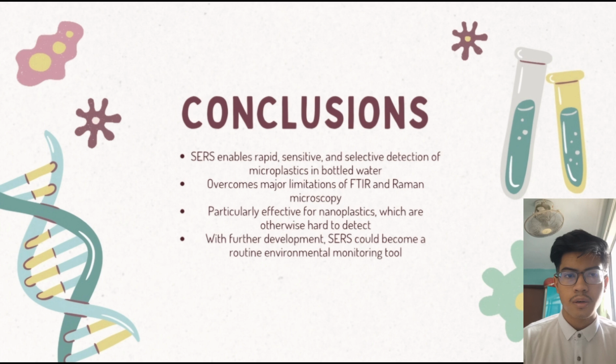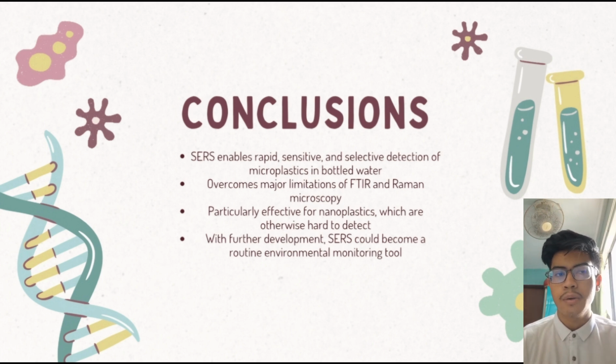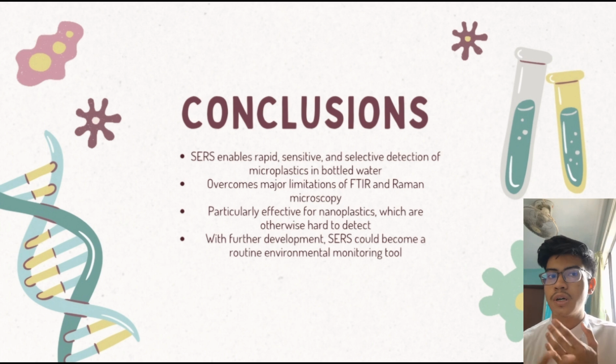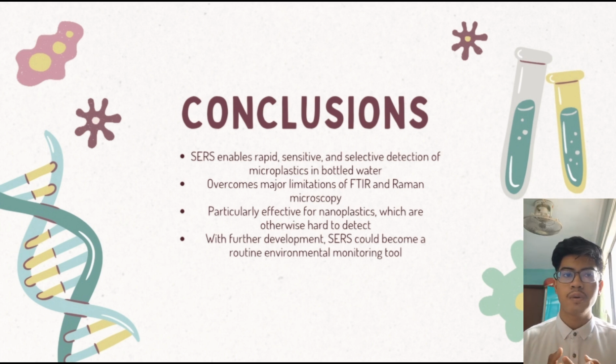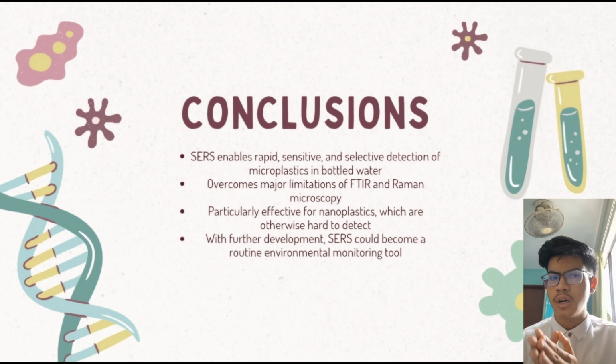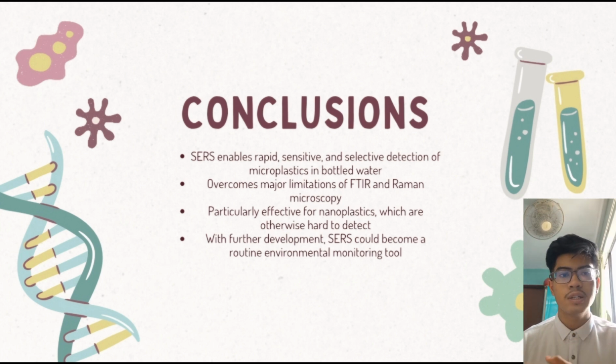So from the article, me and Aiman can conclude that SERS enables rapid, sensitive, and selective detection of microplastics in bottled water. It successfully overcomes many limitations of FTIR and conventional Raman techniques, particularly for nanoplastics, which are otherwise difficult to detect. Recent studies published between 2020 and 2023 demonstrate that SERS, especially when combined with advanced data processing, has strong potential as a routine environmental monitoring tool. Therefore, SERS represents a promising pathway toward accurate and real-time monitoring of microplastics in drinking water.